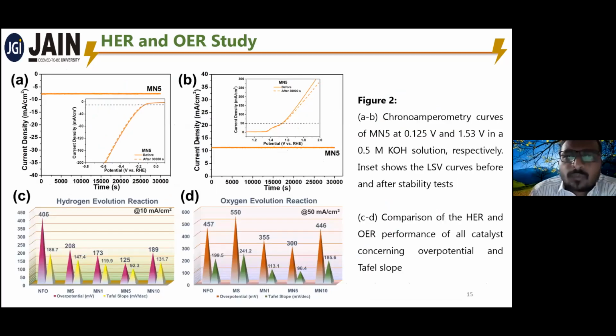We also performed a stability test. From the stability test we can see that up to 30,000 seconds the material is stable, and even after the stability test the electrochemical curves retain their structure. That means the performance is the same after 30,000 seconds also. So the materials are well suited for HER as well as OER studies.